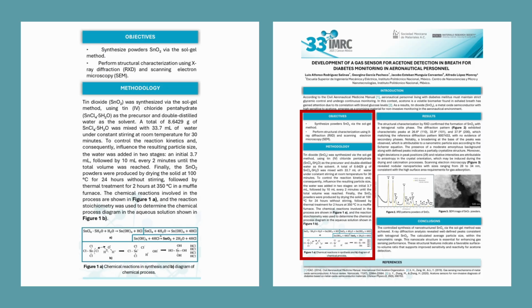Tin dioxide was synthesized via the Sol-Gel method using tin chloride pentahydrate as the precursor and double distilled water as the solvent. The precursor was dissolved under constant stirring at room temperature, and water was added step by step to control the reaction kinetics and reduce particle size. The solution was then dried at 100 degrees Celsius for 24 hours, followed by thermal treatment at 350 degrees Celsius for 2 hours in a muffle furnace.